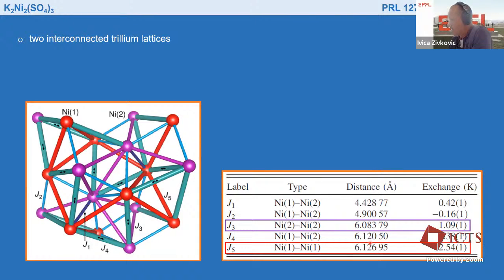But looking at the dominant ones, you can see that the 2 trillium lattices are given by J3 and J5, colored purple and red, while the most dominant interaction is actually the green one, which interconnects the 2 trillium lattices. So in a sense, from this point of view, one can look at what we have observed in